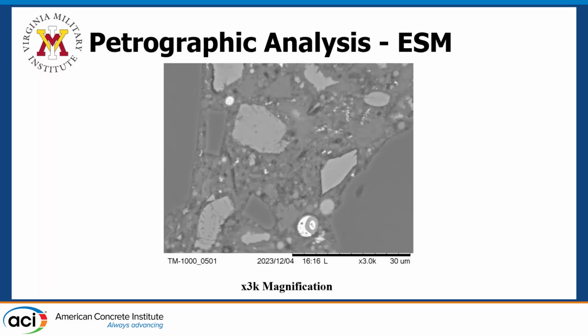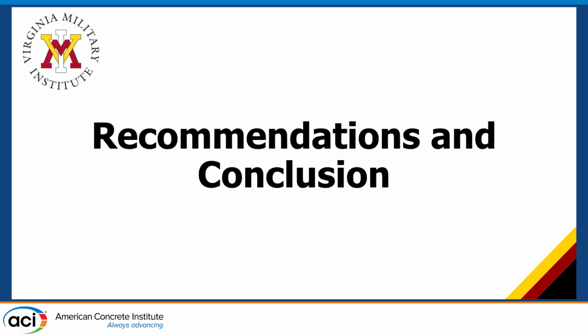It is significantly smaller than normal concrete. Normal concrete is usually 10 to 30 microns. This is sub-micron range. This could be due to a function of the silica fume as well as the low water content. Because of the low water content, essentially the aggregates would not have enough ability to saturate properly, and this is a great thing because it leads to less micro cracking in those regions as well, so higher strength. So, recommendations in conclusion.